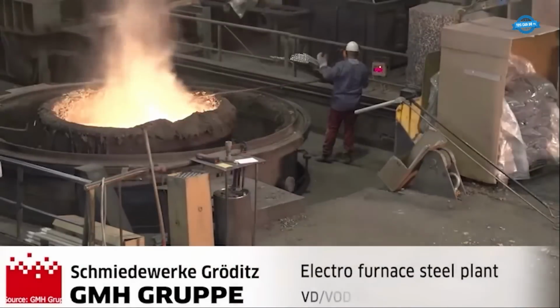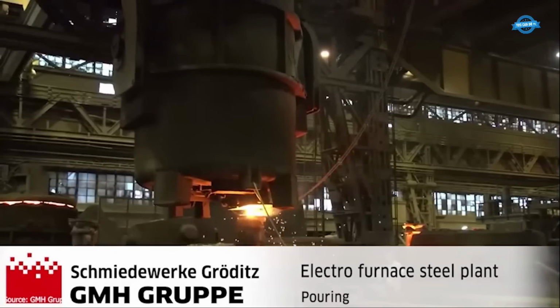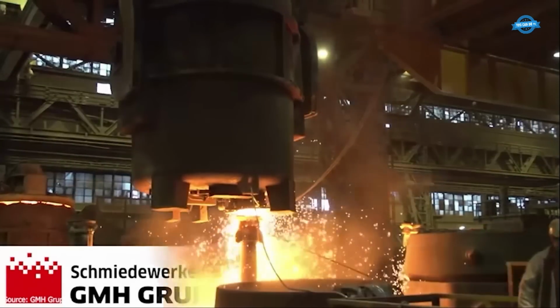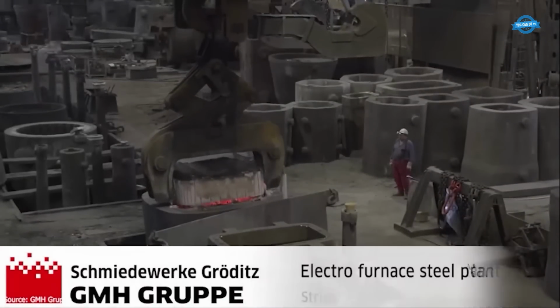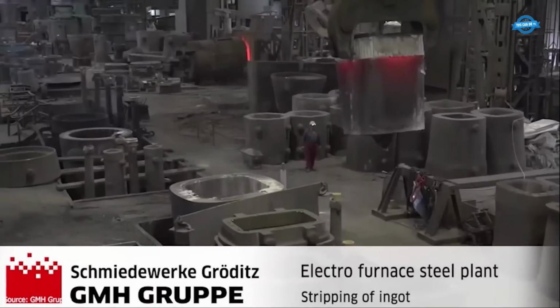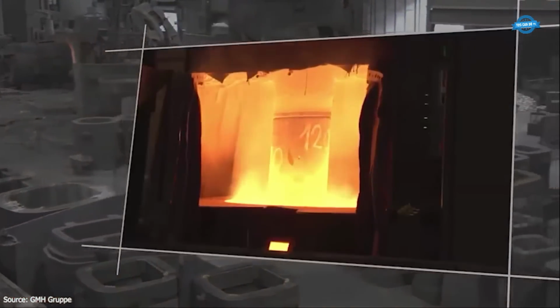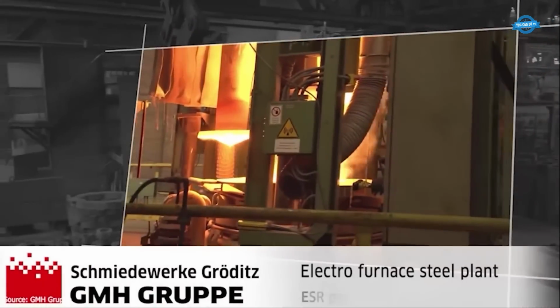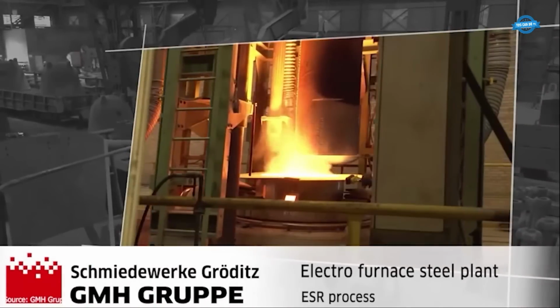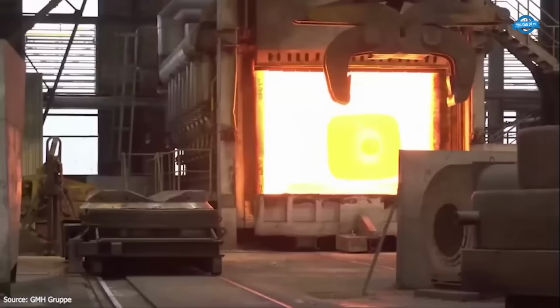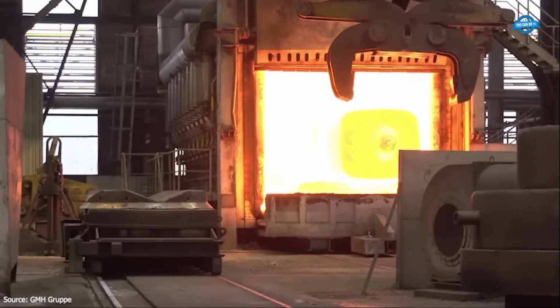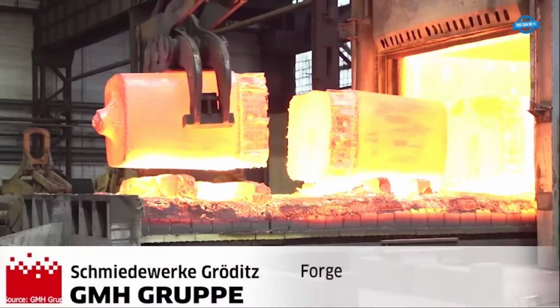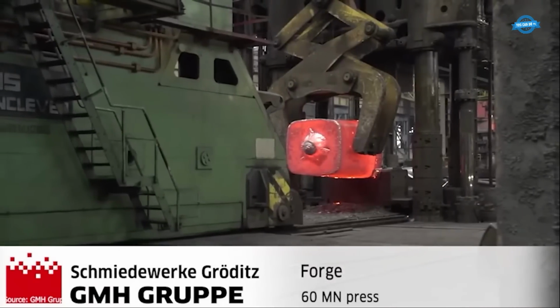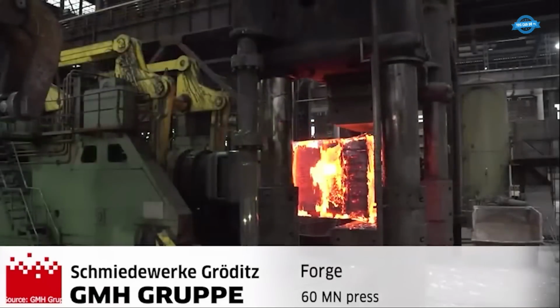The process begins with melting sorted scrap steel in an electric arc furnace, producing up to 50 tons of liquid steel per heat. After tapping, alloy refinement and purging are carried out in a ladle furnace, followed by vacuum degassing. The refined steel is bottom poured into square or rectangular ingots. Electroslag remelting may be used to enhance purity and homogeneity. Ingots are heated to 1,200 degrees Celsius before forging on a 60 meganewtons press.